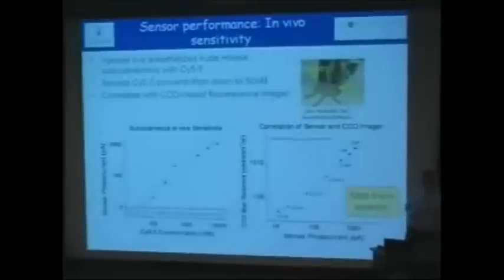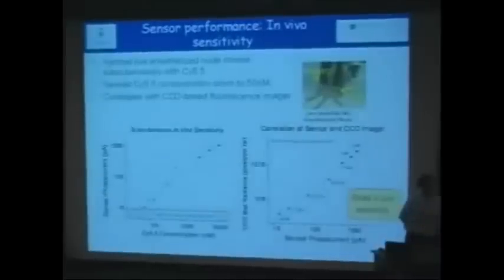We compared it to a giant system called IVIS, made by Caliper and Xenogen, which costs about $200,000 to $300,000, and we have 2 of them now at Princess Margaret Hospital, which we work with. You can correlate what you would get from this CCD-based system on the y-axis and our sensor on the x-axis, and correlate the concentration. As we can see, we have a very good agreement. So in both cases, both the very expensive system and our tiny sensor, the limitation in making the measurement in fluorescence sensing is not the sensor. It is the tissue backscattering that really puts a higher bound.